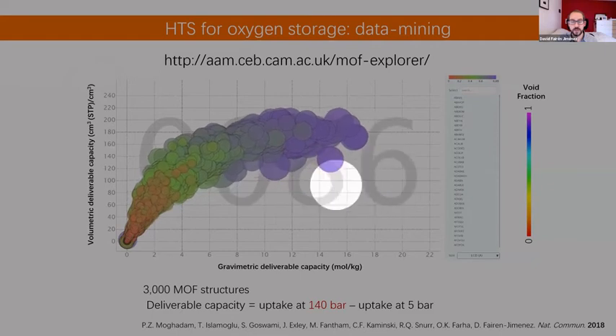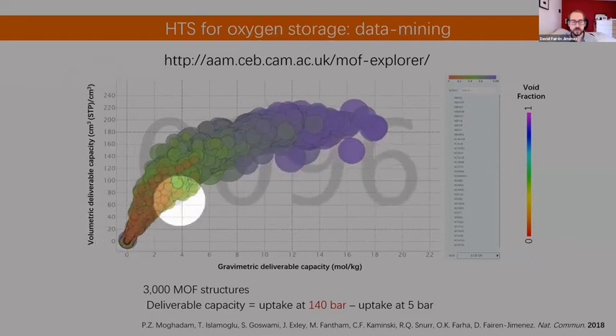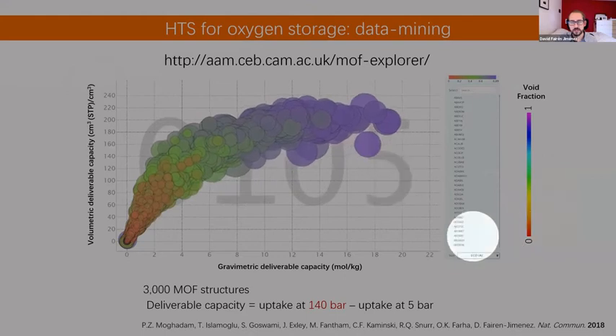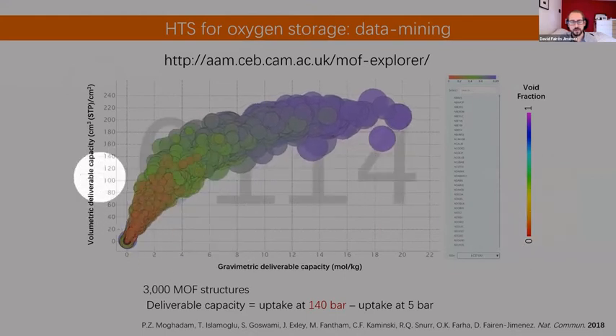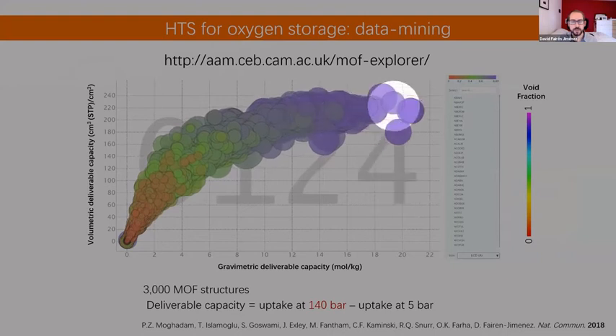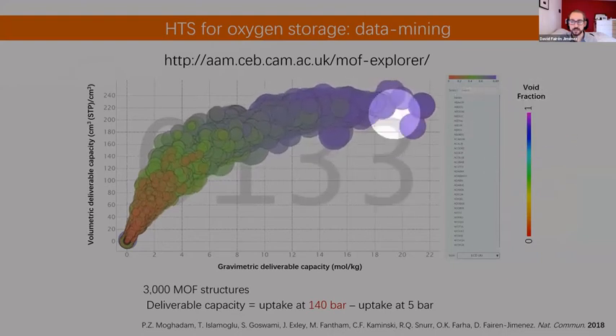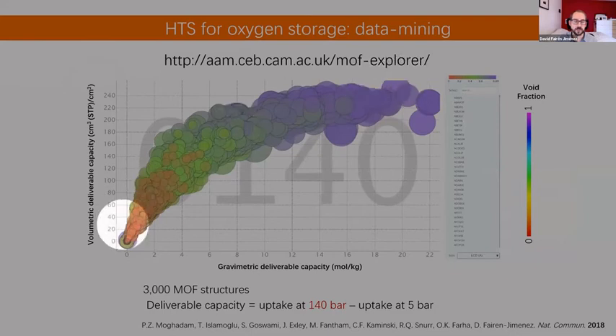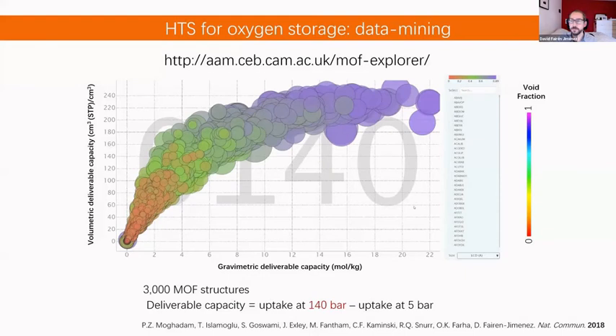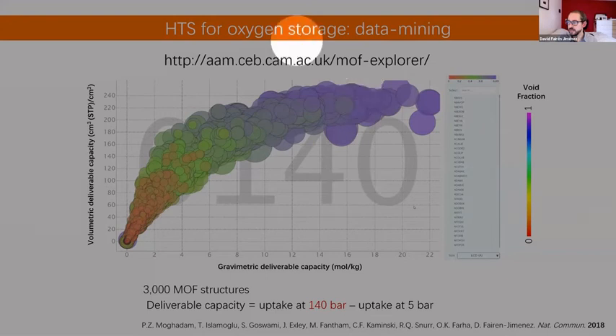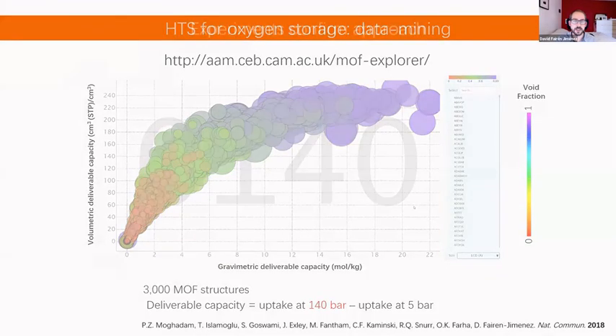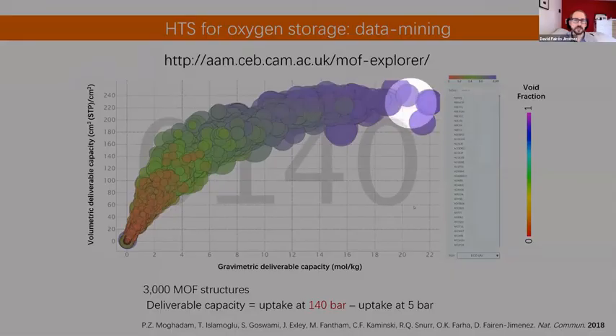You can see that all these orange points, the ones with low void fraction, get stuck at low amounts, whereas all these purple materials with high void fractions were moving quite a lot. They were very low at the beginning, but as soon as we increase the pressure, we are able to move these to higher absorption capacities. Why do we want to have this flexibility here? We want it because we want to be able to select materials almost one by one. Maybe this is going to be the best material, but maybe this is a non-stable structure.